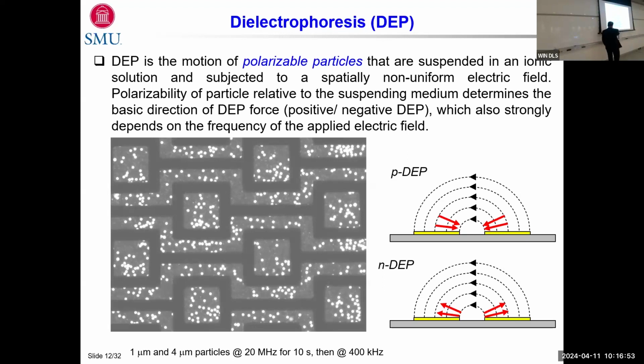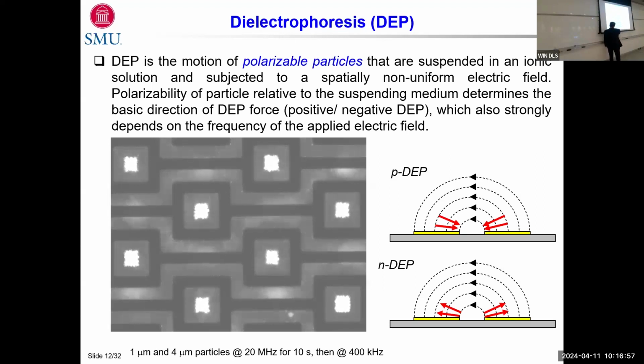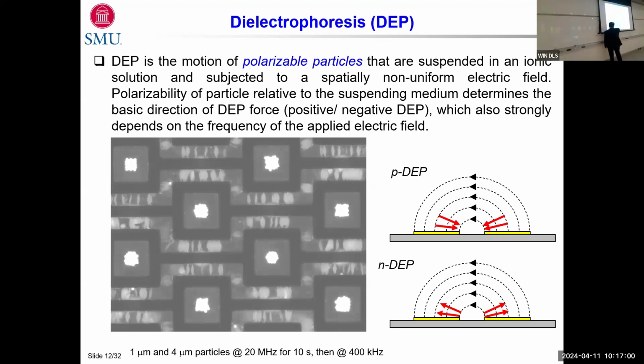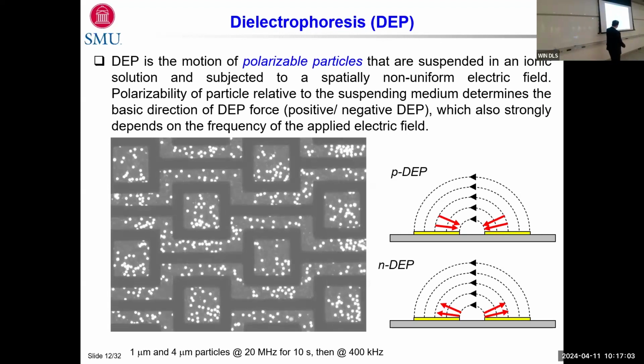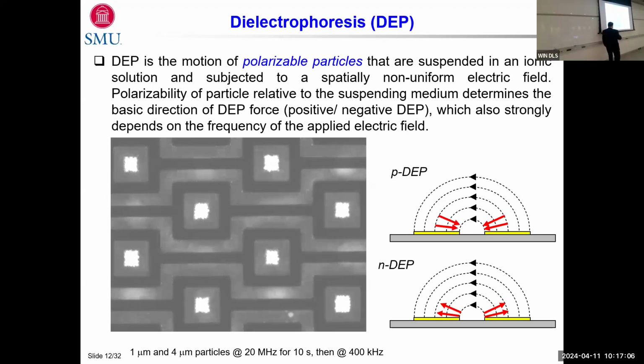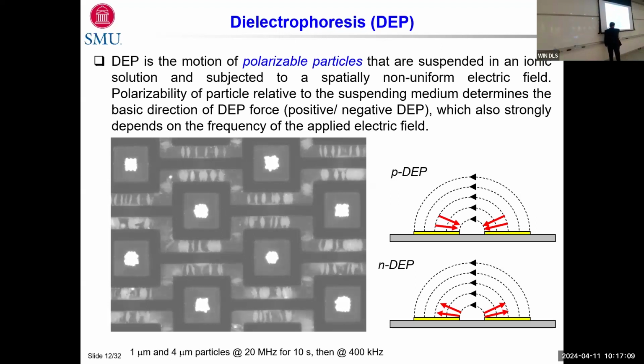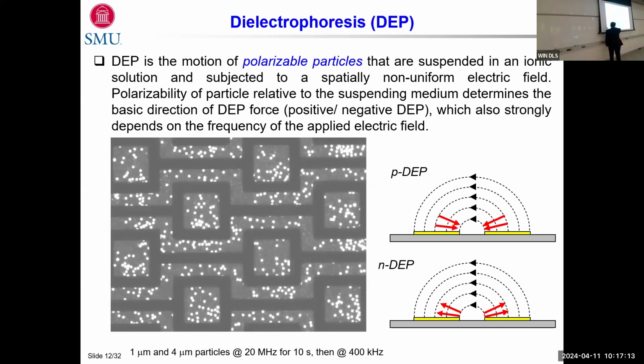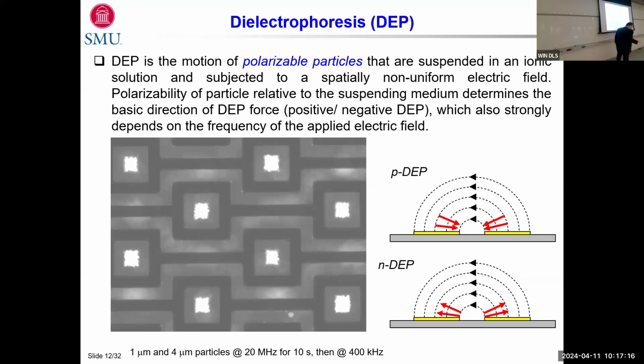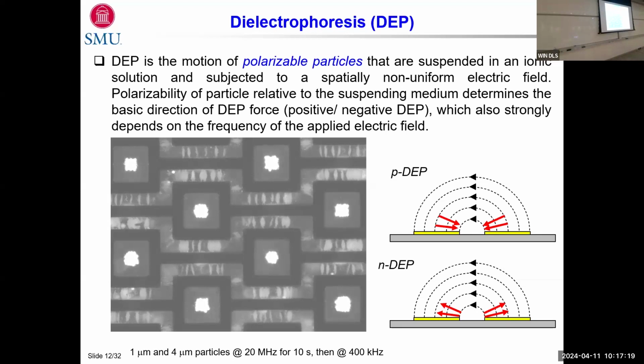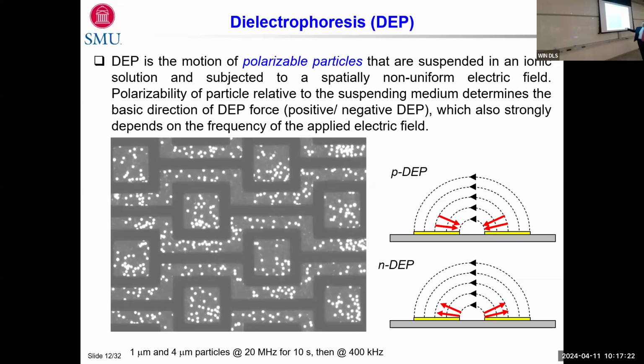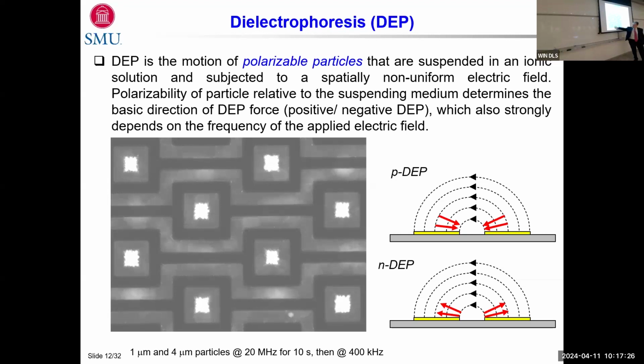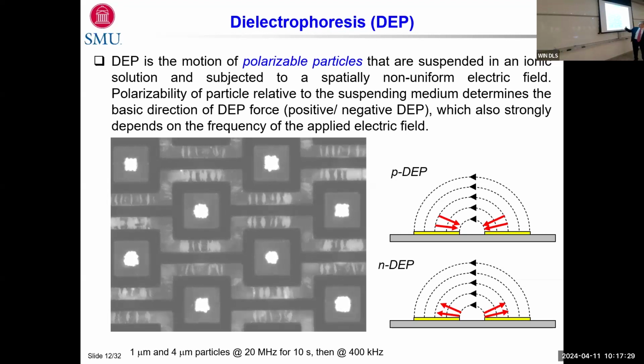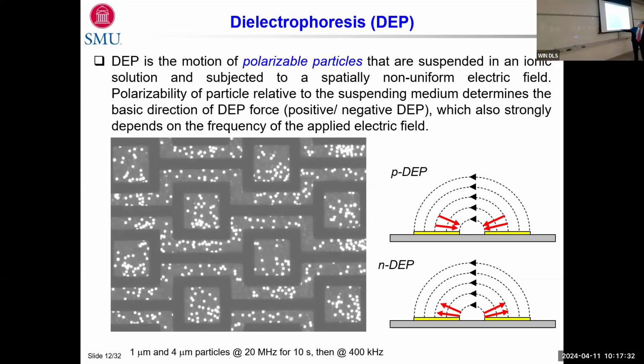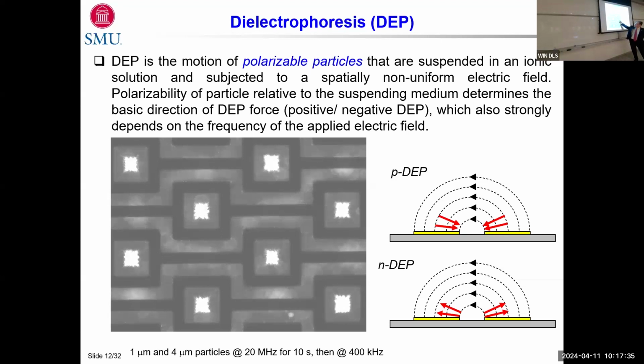I told you earlier on that it is possible to put features on electrodes. In this case, for example, the polarization of one electrode versus the other is changing constantly at 20 megahertz. The importance of this geometry is that at a given polarization, if this is, say, positive, then this square region becomes a potential field minimum, which means that negative DEP will be effective there. So first we're seeing that both particles are going to the field minima, so these are showing negative DEP, and then we switch to 400 kilohertz. Large particles are still staying in the middle, and the small ones are chaining, and that's the positive dielectrophoretic response.